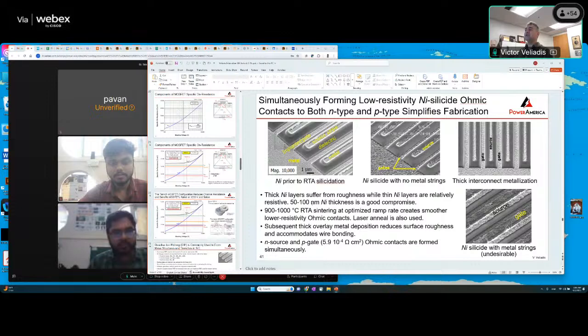If you put a thicker layer, the danger is that some of that nickel that you're putting down will not react with the silicon carbide underneath to form a silicide layer, and then that will create problems when you come down with the aluminum layer. So, in a lot of cases, if you put more nickel, you have unreacted nickel that you need to basically get rid of. And that's a very painful process.